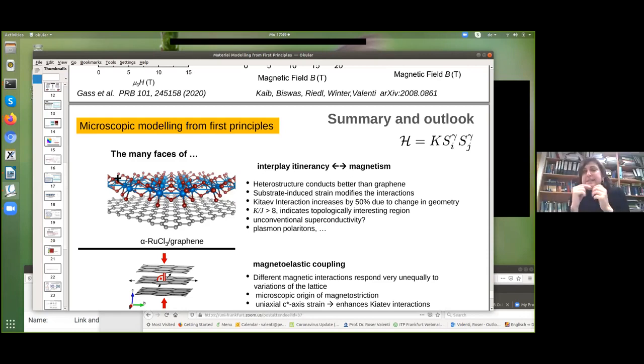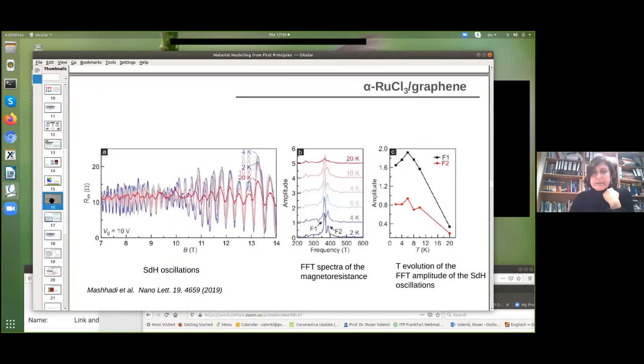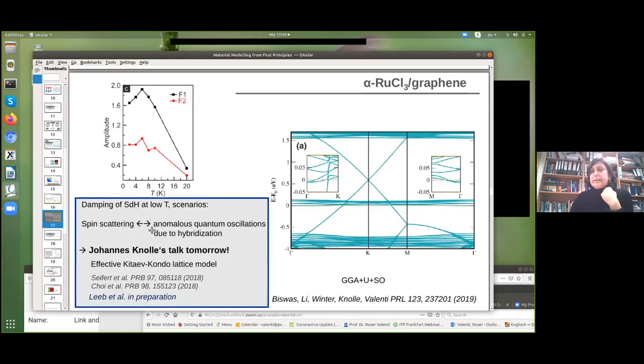But let me just answer on my side shortly. Indeed, there are two scenarios for understanding these measurements here. One scenario is that we know that bulk ruthenium trichloride orders at about 7 Kelvin, which is the reason why you also see these anomalies. That could be because of spin scattering, because the ordering is setting in, that you are having these features. But an alternative explanation is that we have been seeing this very strong hybridization between ruthenium trichloride and graphene, and one could consider that this is a consequence of this strong hybridization. A model that is very suitable to describe this type of phenomena is the Kitaev-Kondo lattice model. But this is what Johannes will present tomorrow.